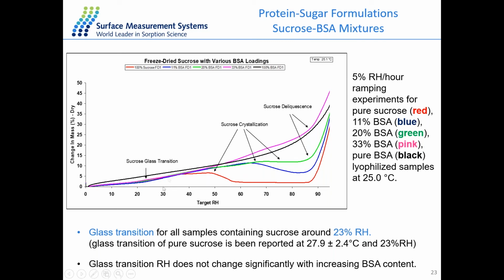And what we can observe here is all the sucrose containing samples have a glass transition point around 23% RH. And this value is quite consistent with the literature value for the pure sucrose sample, which is around 23% RH at around 25 to 30 degrees. And with different loading concentrations of the protein, as you can see, the glass transition has very little impact from the loading concentration. The lines are just overlapping here. So protein has very little impact on the glass transition.